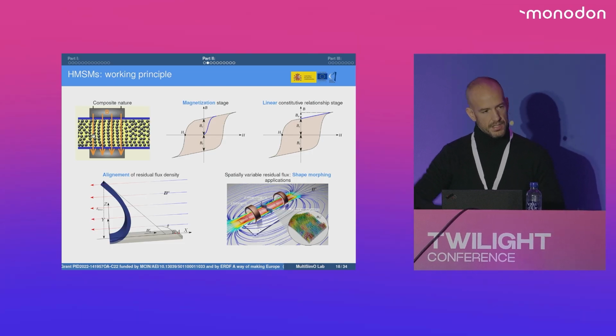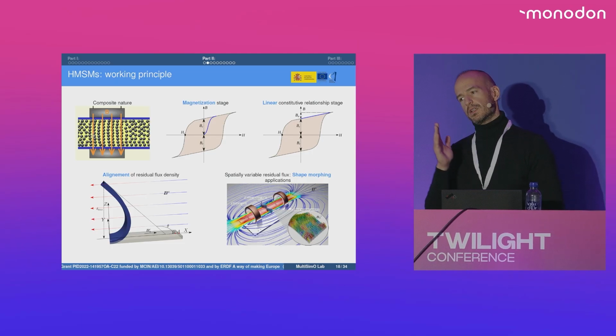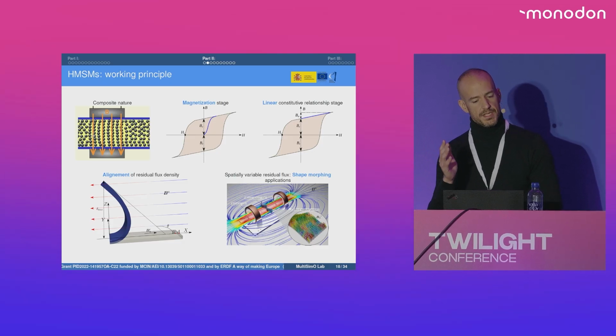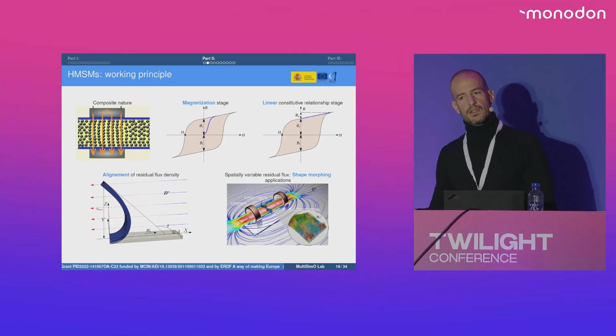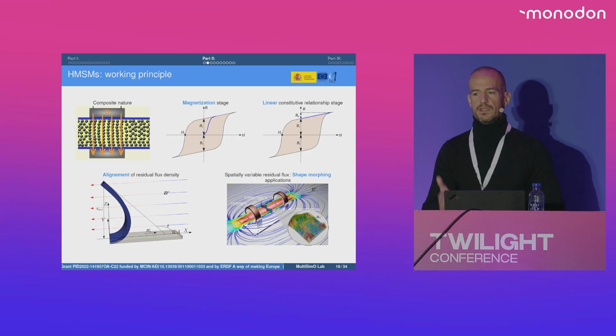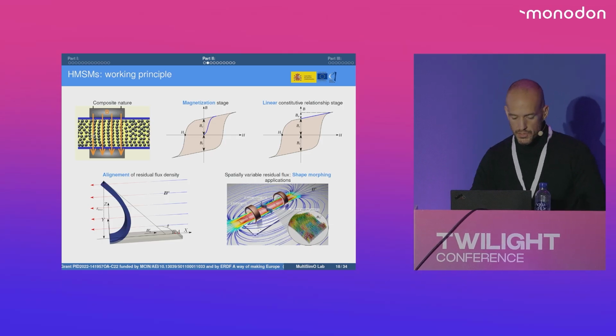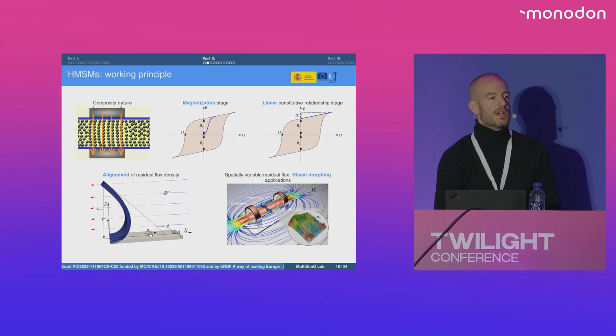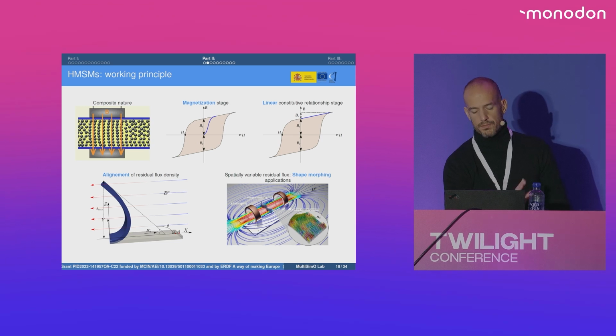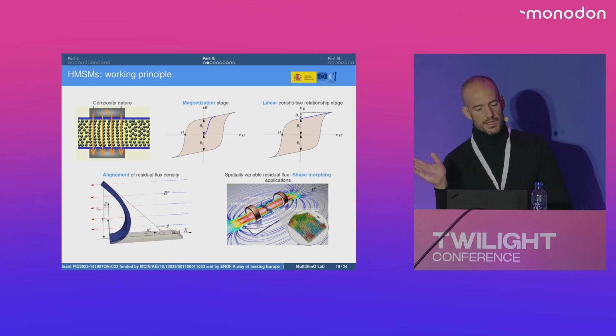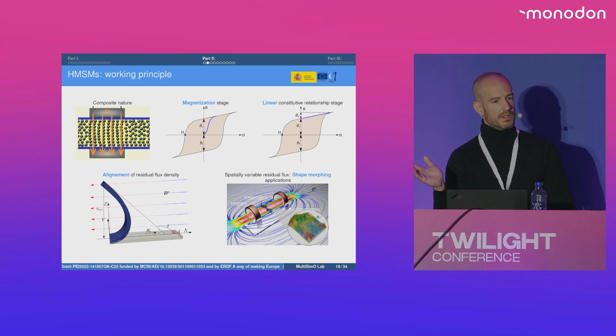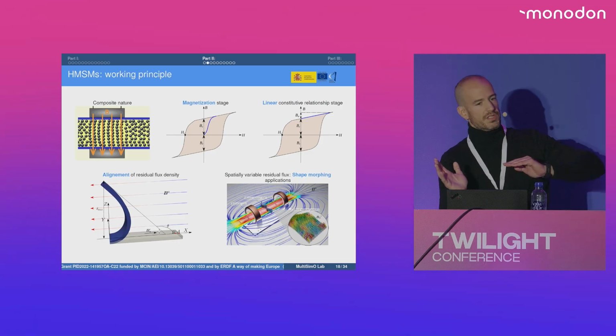You can see it here. They are oriented, and they get a remnant magnetization, and that magnetization is permanent. So if you remove the magnetic field, the particles are still aligned, and they are still magnetized. Okay? So you can see what happens in this device here. It has been magnetized in this direction, uniformly magnetized in this direction, and then we have removed the magnetic field. And once you remove it, the particles retain their magnetization.